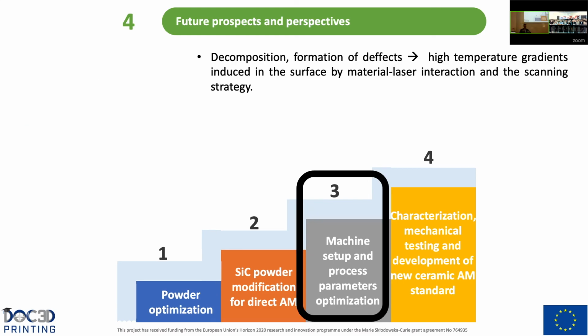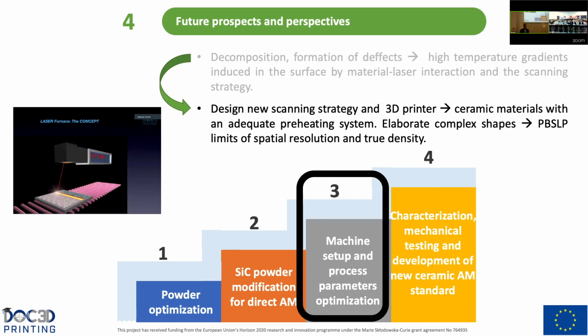Next, regarding the machine setup and process parameters, here we have observed some decomposition and formation of defects during the process due to high temperature gradients induced in the surface by the material-laser interaction and the scanning strategy. So in this regard, we need to design a new scanning strategy and a new 3D printer adapted to ceramic materials with an adequate preheating system. And moreover, we should elaborate more complex shapes to study the limits of spatial resolution and density of this technique.